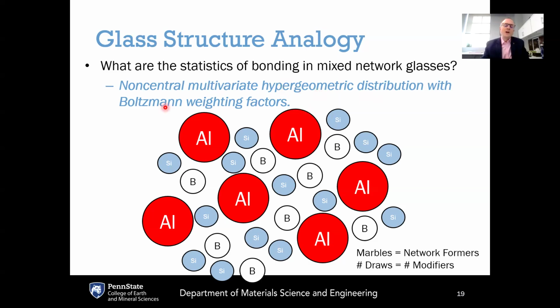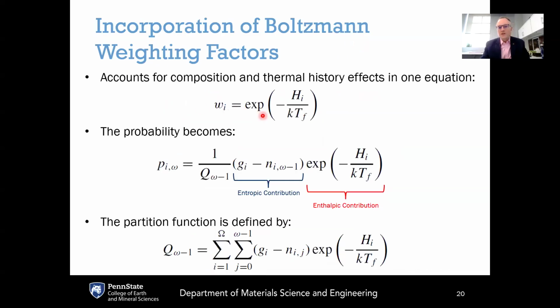The Boltzmann weighting factors come in because the Boltzmann distribution is the relevant probabilistic distribution for describing the statistical mechanics of the system. So the Boltzmann weighting factor here, W sub i, is just a Boltzmann probability factor, e to the minus h_i, which is the enthalpy of that particular association, or it could be the potential energy of that particular association, divided by the amount of thermal energy where the supercooled liquid gets frozen into the glassy state. If we take that as the fictive temperature, so the fictive temperature is the temperature where the supercooled liquid is effectively frozen into the glassy state, then kT_f is Boltzmann's constant times T_f. That's the thermal energy where that glass transition happens. So this is our energetic weighting factors here, or enthalpic weighting factors.